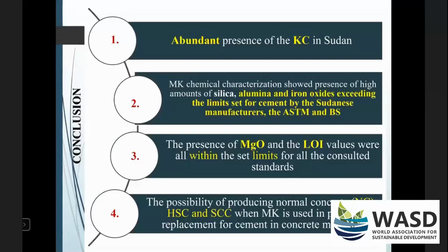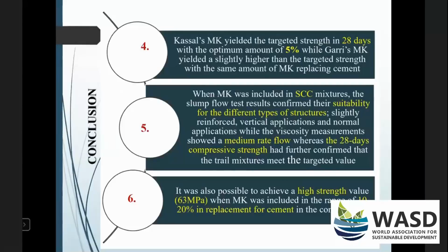In the 3 scenarios that we investigated, we were able to get good results out of the use of the metakaolin. We found out that the location from which we got the source kaolinite clay makes a difference. For example, Kassal's metakaolin yielded the targeted strength in 28 days, with an optimum amount of only 5% of metakaolin replacing cement, while from another location, which is Garri, the metakaolin yielded just a slightly higher than the targeted strength, with the same amount of metakaolin replacing cement.